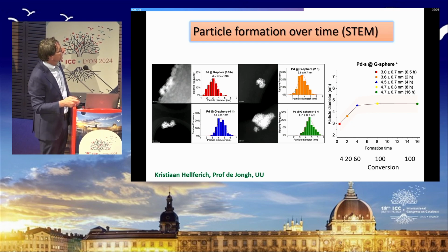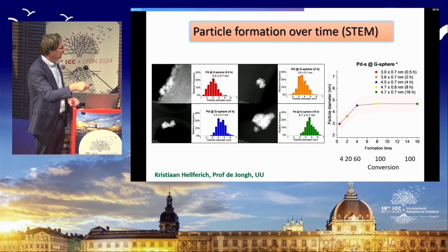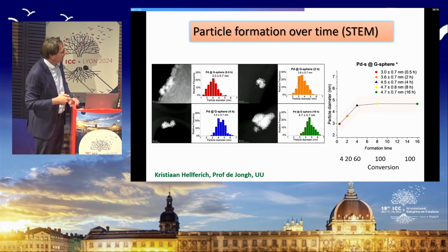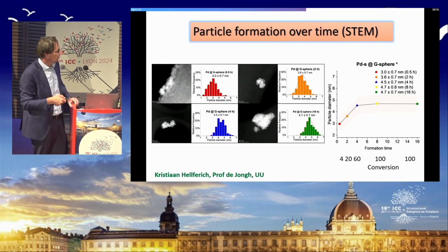So we monitored the particle formation over time by electron microscopy, again in collaboration with the group of Prof de Jongh. And here you see the particle diameter as function of formation time, where here we have 4% conversion, 20% conversion, 60% conversion, and 100% conversion.